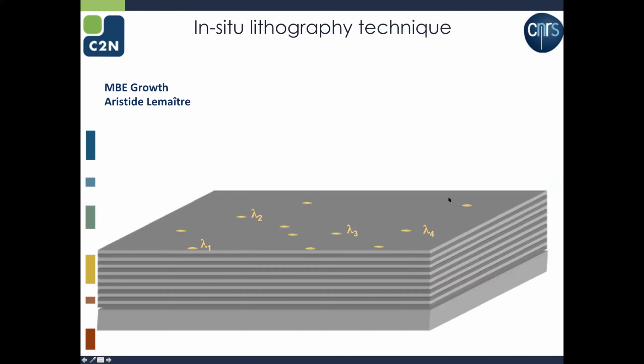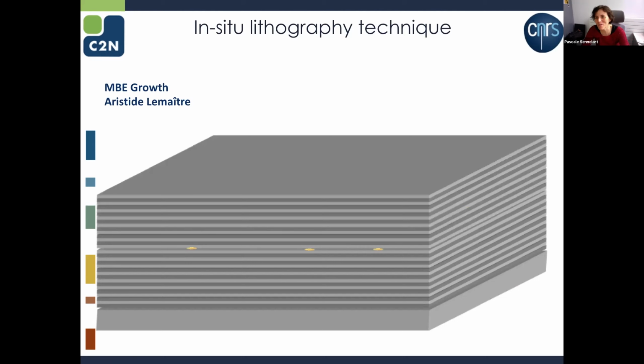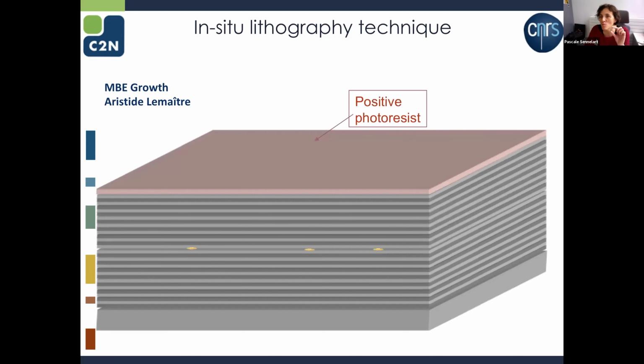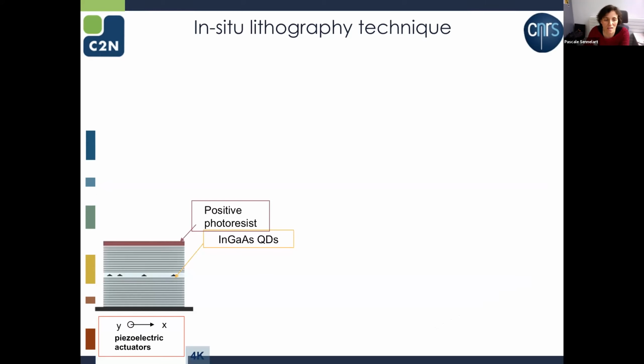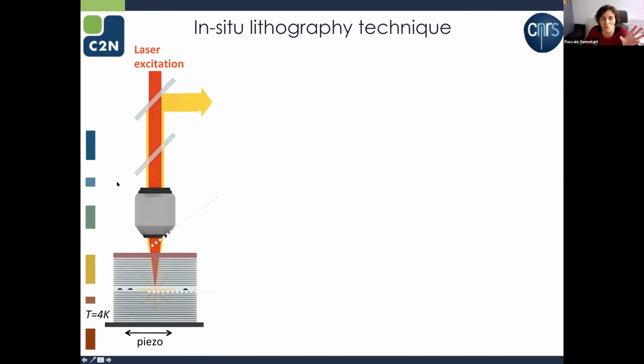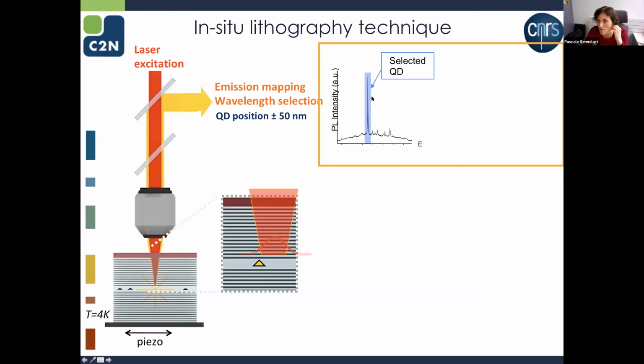And we grow a second mirror. And the idea after that is to put a photoresist. A photoresist is a polymer that we will use to draw a pattern on it. So we take that, we put that at low temperature at 4 Kelvin when we can measure the quantum dot single photon emission. And the idea is that we will measure where the quantum dots are by optical means. We excite with a laser the quantum dot emission. We find a nice quantum dot. It shows a very sharp emission line in the spectrum.